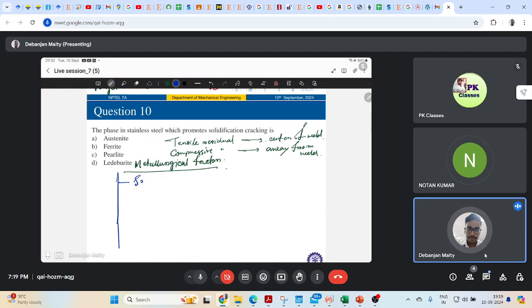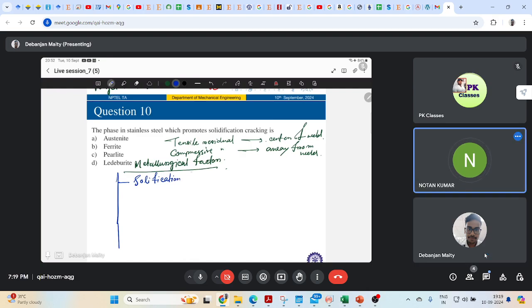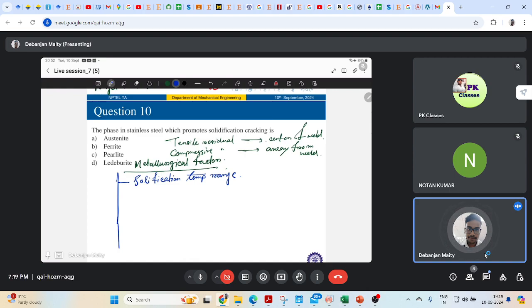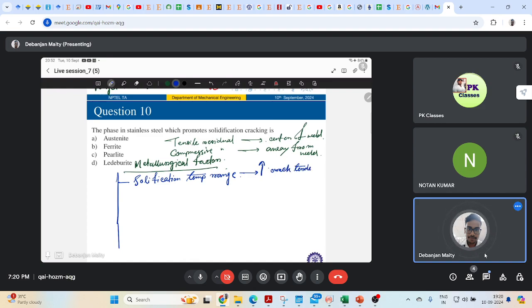Of course, one is solidification temperature range. Generally speaking, the wider the solidification temperature range, the larger will be that mushy region in your weld metal, right? And the larger the area that will be weak and susceptible to solidification cracking. So if this is increasing, cracking tendency will increase. So people do some alloying to reduce the temperature range. The solidification temperature range of an alloy will increase as a result of the presence of some impurities, such as sulfur and phosphorus in steel or nickel based alloys.